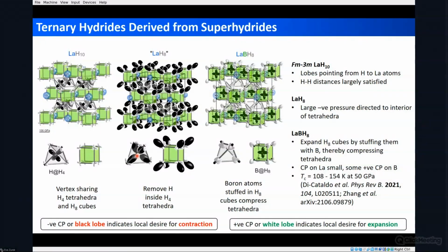And so one of the ways to relieve these negative pressures is to expand the cubes by putting boron or beryllium or other atoms within the cubes, and then you get this kind of a minimization of the excess chemical pressure. And this LaBH8 or BeH8 or other types of compounds that have been predicted in this family, this is one of the reasons why they are stable, and they are stable to lower pressures than some of these really high pressure LaH10 systems.